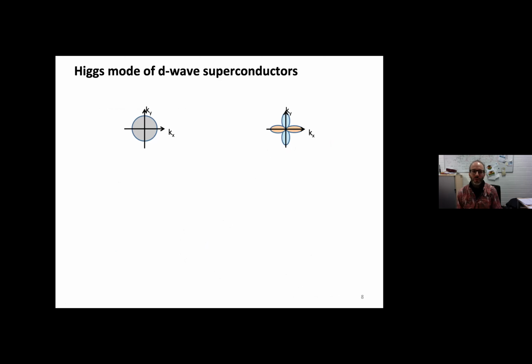In the following, we are now interested to really look at the Higgs modes in unconventional superconductors. And here, most important are the systems that don't show this conventional S-wave superconducting systems where we have an isotropic gap. For example, we are interested in D-wave superconductors like the high TC superconducting cuprates, where we have a momentum dependent gap of this system. And this has severe consequences for how Higgs modes in these systems show up.